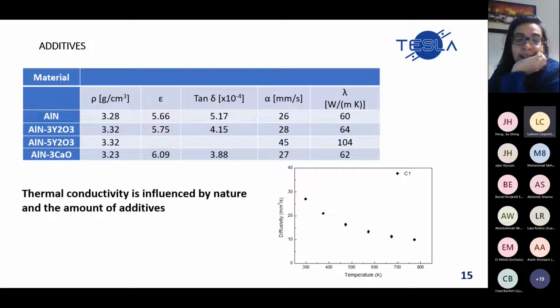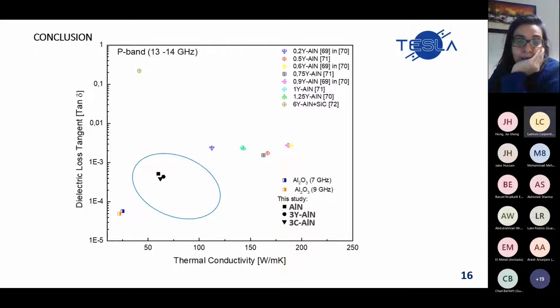So, after developing this type of materials, we decreased a little bit the dielectric loss. Comparing to the theoretical values we found in the literature, it is low, but as Basel showed, it is not low enough.